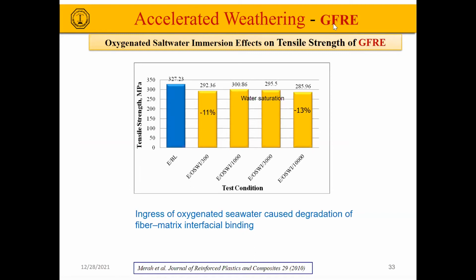Accelerated weathering of GFRE. We put the pipe sections into oxygenated salt water, and we looked at the tensile strength after 300 hours, 1,000 hours, 3,000 hours, and 10,000 hours. After 300 hours, the tensile strength reduced by about 11%. Then up to 3,000 hours, maybe the water uptake was saturated. As we will see later on, there will be a saturation after a certain number of hours. And the maximum after 10,000 was a reduction of 13%.